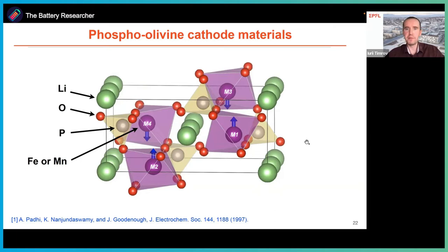So before I say that, we can use DFT plus Hubbard and we can determine Hubbard parameters for each transition metal ion. I would like to highlight that during the delithiation process, when we start removing lithium one by one, some transition metals will change their oxidation state. And the Hubbard U parameter will be different for different transition metal elements, depending on the oxidation state. So let's see what we obtain.